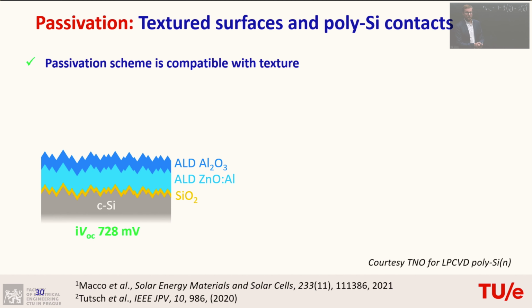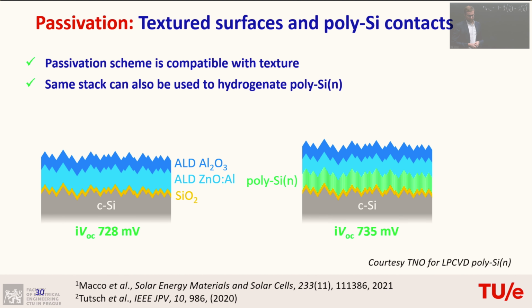So then, is it also possible to combine this with already existing interesting architectures in crystalline silicon cells? So we saw before that polysilicon contacts or TOPCon-like structures are now very popular. Texture is what you need anyway to improve your light trapping in your devices. So basically always you have textured wafers. And here we looked at the passivation of such samples. You see, if you have a textured wafer, your implied VOC is already quite nice and high. And if you take n-type polysilicon, as you would have in the TOPCon configuration, also in this case, you can reach really high implied VOC values. So this is actually quite promising because you can combine it with those already existing structures. And n-type polysilicon is a good contact, but it is also quite absorbing. So it would be nice if you can put a very transparent conductor on top of it.